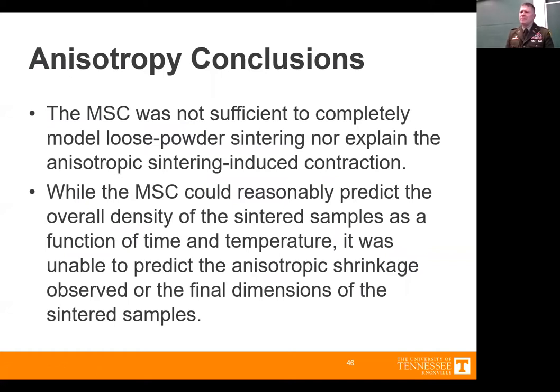Additionally, some of the conclusions: the master sintering curve just appears not to be able to quantify or accurately predict the anisotropic shrinkage. Overall, it was able to model very well the actual densification of the object if you ignore any densification gradients and just look at the total density of the object. So it was very successful at modeling and predicting that densification. However, because the shrinkage of these objects was anisotropic, it shrank more in one dimension than the other, the master sintering curve isn't able to capture that. It isn't able to predict that at all. And so if you need an object that's precise in its measurements after it's sintered, then it's very difficult to see how the master sintering curve will enable you to predict that anisotropic shrinkage.